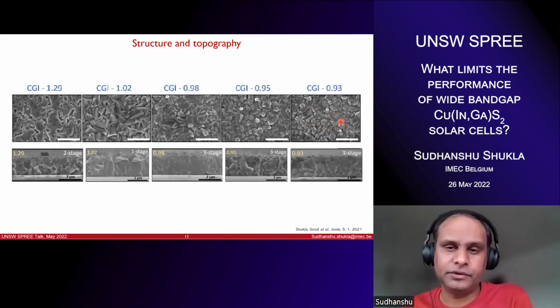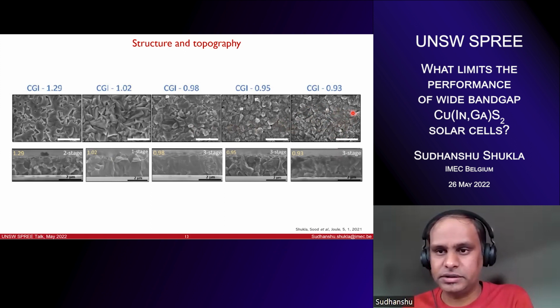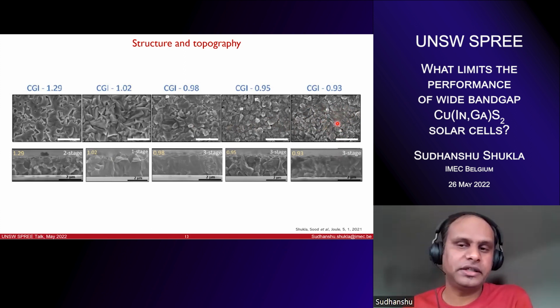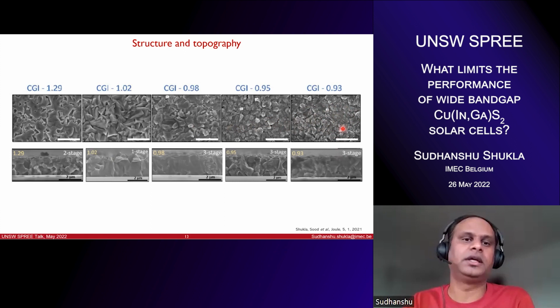And they are speculating a few things, which I'll not go into the detail, but I think you should take into account these fringes as well. When do they appear? If these fringes are coming in your SEM, you notice all this, you're probably going to guess the absorbers are okay for making devices. This is what my experience is with these films.